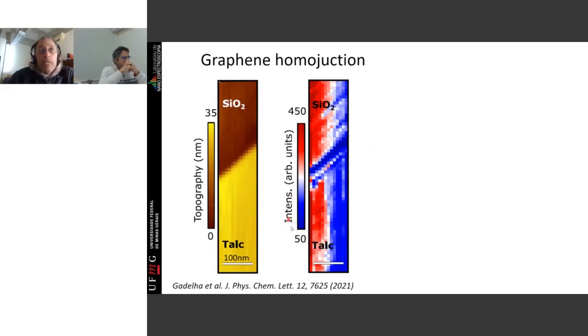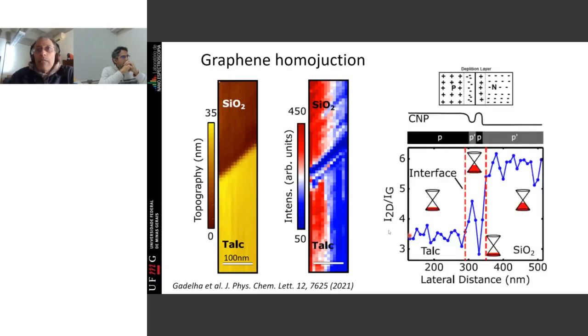And if I look now into the intensity of a given peak, and I cross the junction, I see that there is actually an oscillation, okay? Let's make a line here. Look at the intensity of this Raman feature normalized by the other feature. These are the two features established by the Koreans. This intensity ratio has one level when you are in talc, and then at the interface, it goes up, down, and up again, and then it goes into another level, okay?